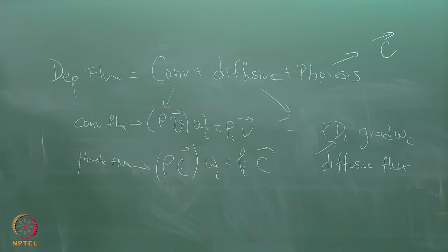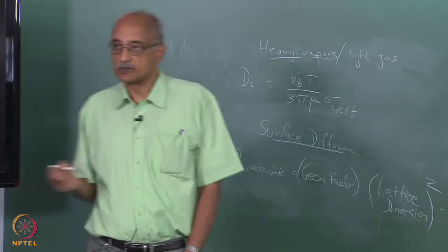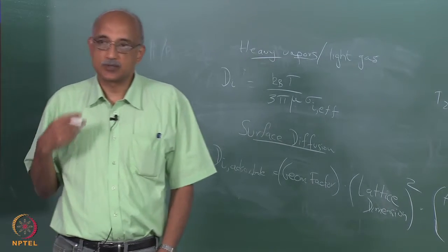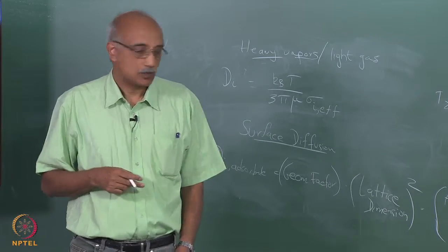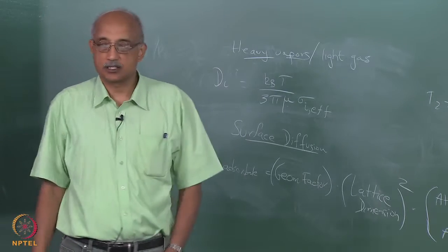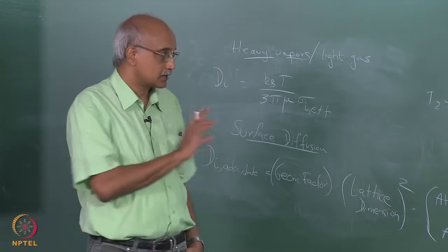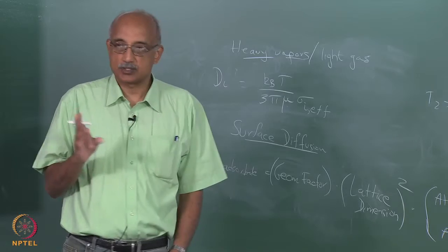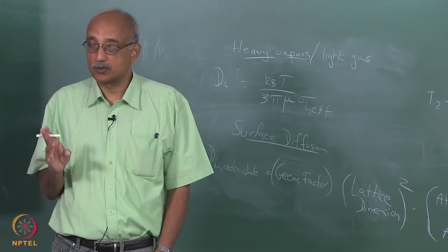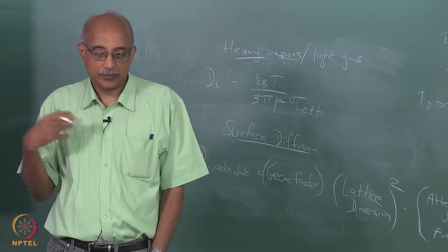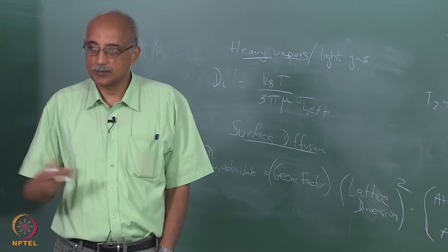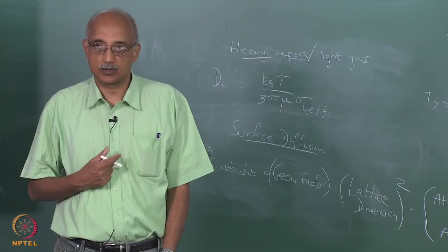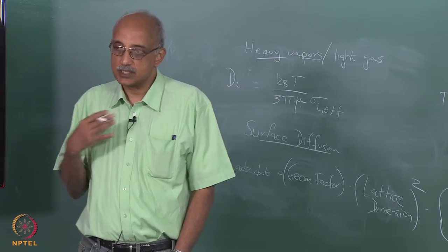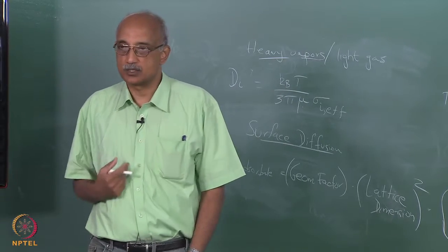So, the challenge really becomes how do you estimate this phoretic velocity c for various fields. In some cases, it is obvious, some cases it is not. So, we will deal with that in a couple of lectures, because it is these correction factors to the deposition flux, which if you are not careful and you neglect, you will not be able to estimate the deposition flux in a CVD reactor very accurately. And that can lead to very misleading conclusions about the design and operation of your CVD reactor.